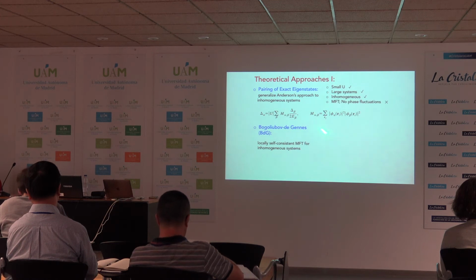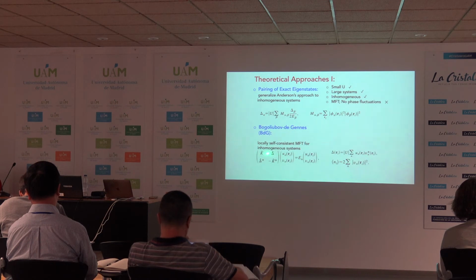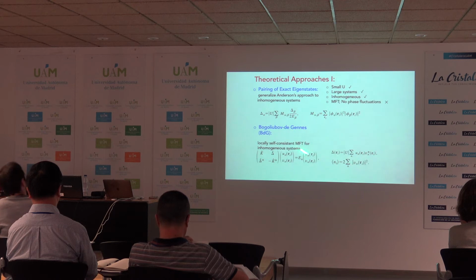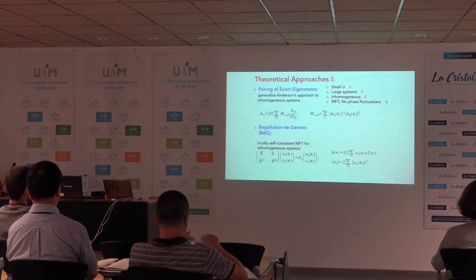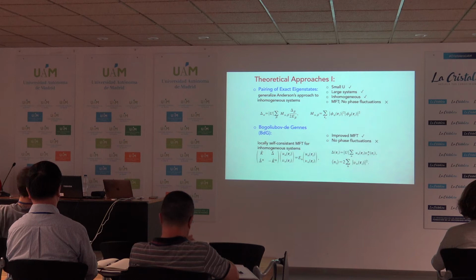You can go beyond that, still within mean field theory, do Bogoliubov-de Gennes mean field theory, where you allow your inhomogeneity in the delta potentials and the densities and you solve for that self-consistently at each site. And from that you can get the local pairing amplitude delta and the local density for a given random potential that you input into the system. So these methods are quite powerful, but they ignore any phase fluctuations.